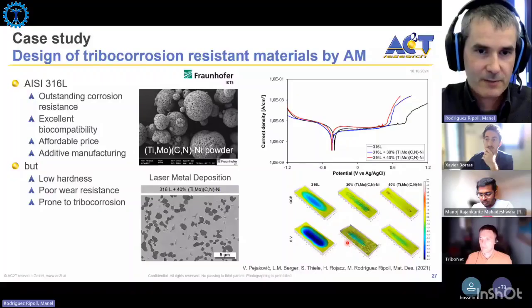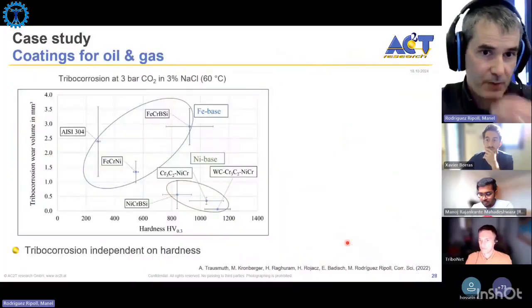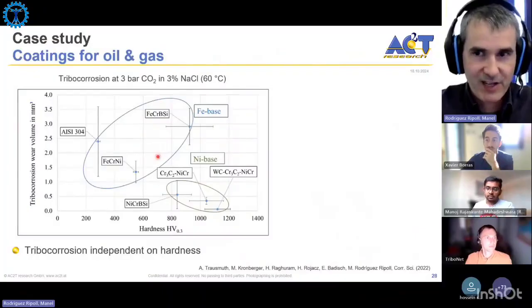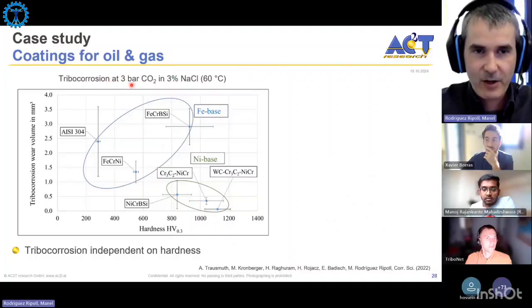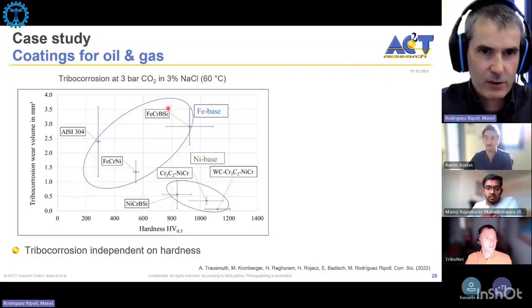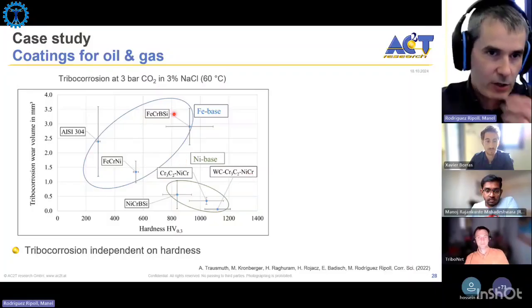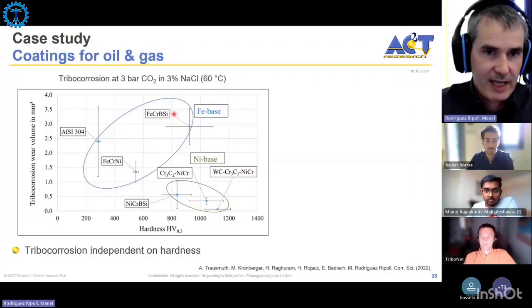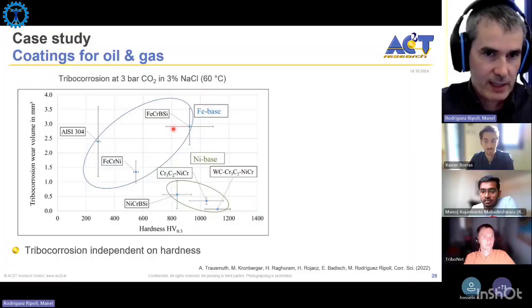So you can also use the same concepts of this OCP experiment, these potentiostatic experiments, for investigating or designing tribocorrosion resistant materials. Another thing you can do, for example, is to get this kind of measurements that we did at 3 bar CO2 pressure. So this is a bit different. So we have sodium chloride at 3 bar of CO2. So we have CO2 corrosion. It is slightly different. I will not enter into much detail. So we are having the formation of iron carbonates because we don't have oxides. So we are promoting, for example, here for the iron alloys, the formation of carbonates, and we don't have oxygen here dissolved, so that we are working under anoxic conditions.